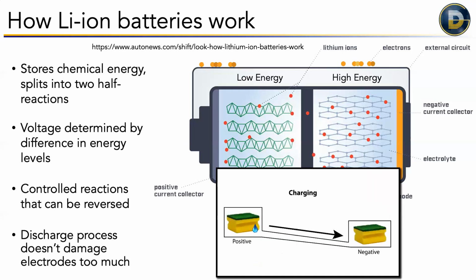So the important thing is that whatever discharge process happens, it doesn't damage the electrodes too much to the point where you can't reverse things and put everything back where it was. And essentially that's what you're doing when you're charging. You apply a voltage when you charge, and that essentially tilts the whole table, if you will. It tilts the energy landscape and drives the current or the water back the other direction. So like I said, the voltage is the difference between the two materials on each side.